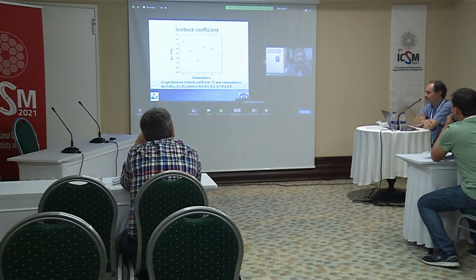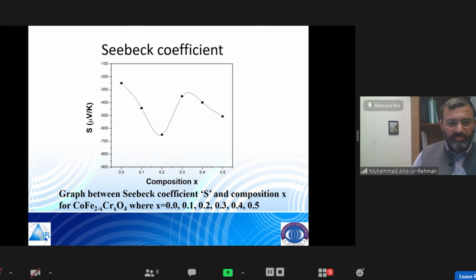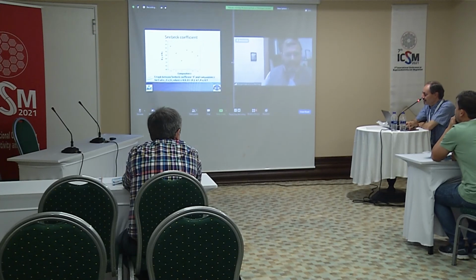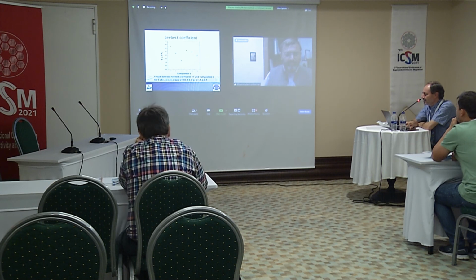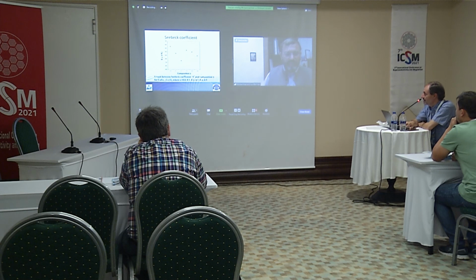Actually, up to the concentration of 0.2, the drift mobility is decreasing and then it is increasing. Basically, it is the drift mobility, the movement of the carriers, that is causing this difference. I guess that is related to the doping level that you change. Yes, it may change the oxygen stoichiometry in the system, and also the defect content and distribution. That is the main reason.